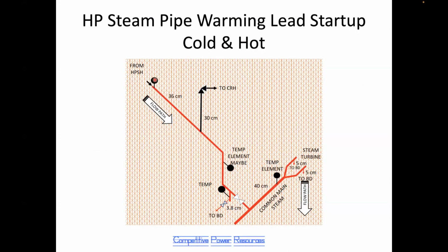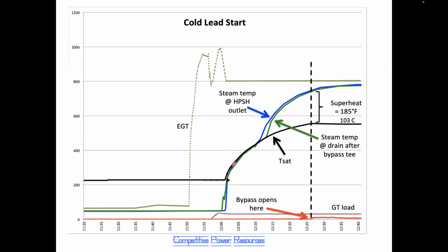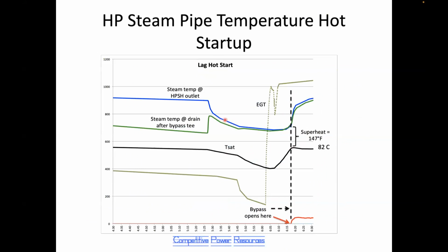But this section, this temperature and this temperature during the hot start, they're already superheated. Those are the same temperatures. So when the bypass opens, again, we've got 82C of superheat. So there's no problem during the hot start with the bypass, primarily because that critical pipe work did not need to be heated. It was already hot and dry.